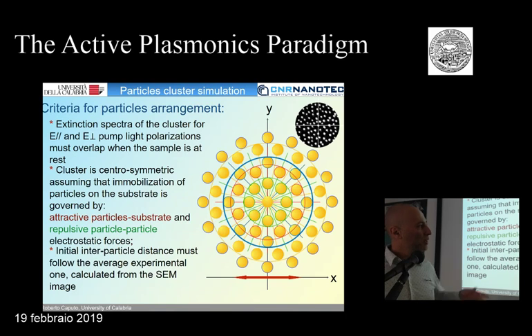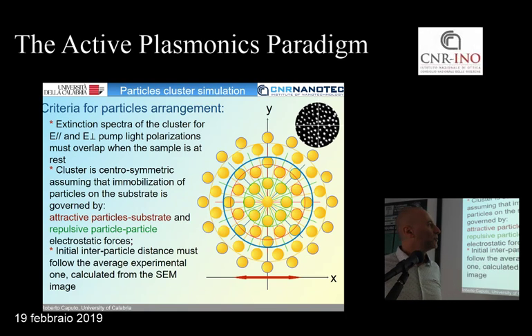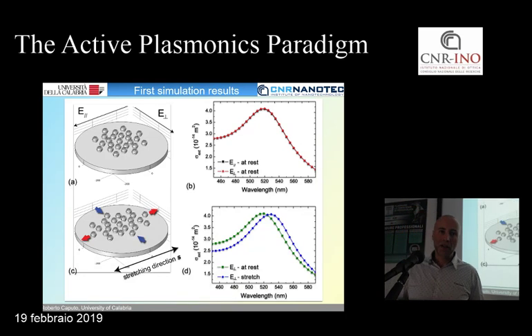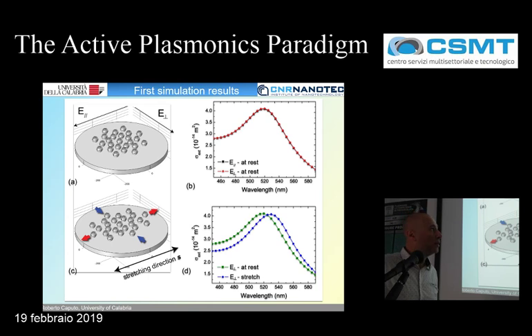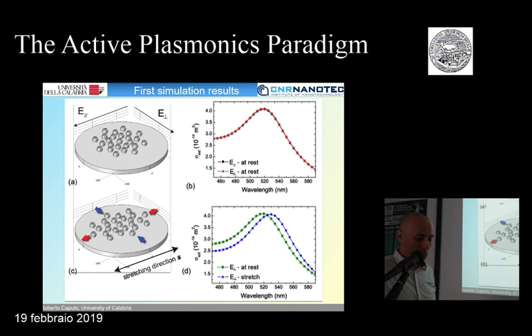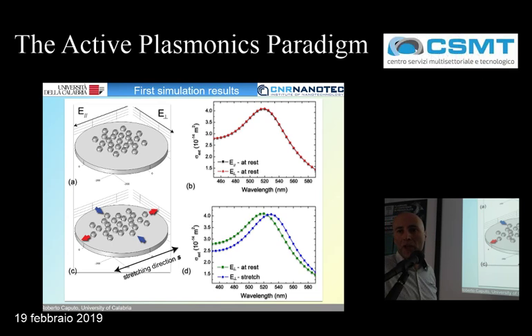So at the end we gave an average distance between all the particles of this numerical cluster, to respect the real case. By making the first simulations, we observed that indeed you can find, at least in a qualitative way, the experimental behavior. So you observe a shift of the resonance when you pump with the polarization perpendicular to the stretching direction. And at the same time, you don't see any difference at rest. So the two spectra are the same. This is confirmed in the experimental case.